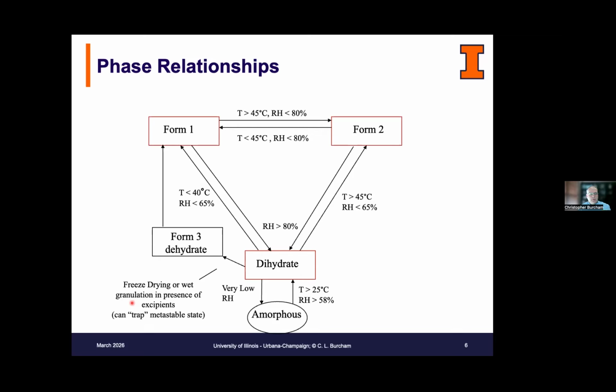And you develop a phase relationship map similar to what's shown here, where we found that we had two anhydrous polymorphs enantiotropically related to one another, where that conversion temperature is about 45 degrees C, and also the formation of a dihydrate above 80% RH. There's a couple of unstable forms, but these were the three that were really in play. And as most companies would do, Form 1 was initially selected for development.